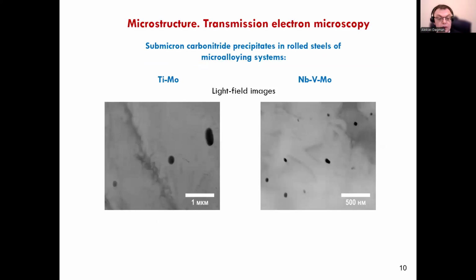In most rolled steel samples, submicron carbonitride precipitates of about 0.1 to 0.5 microns in size are present in small amounts, figure A, in the steel of the niobium-vanadium-molybdenum microalloying system. In steel cooled after the highest end temperature of hot rolling, 880 degrees centigrade, a large number of precipitates up to 0.2 microns in size were observed. Figure B.